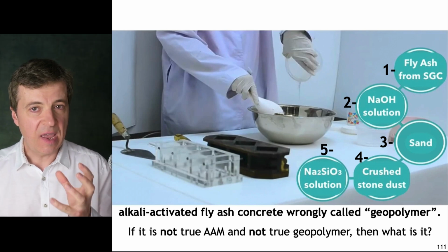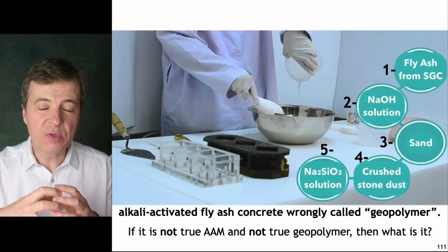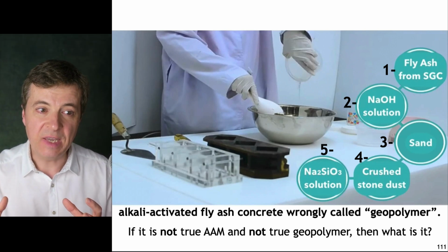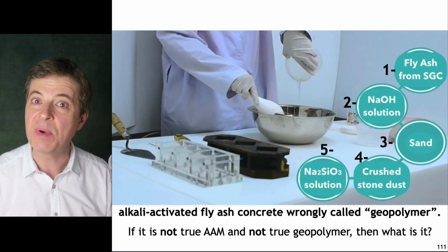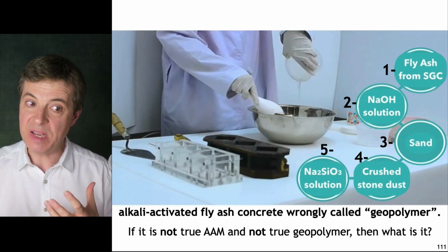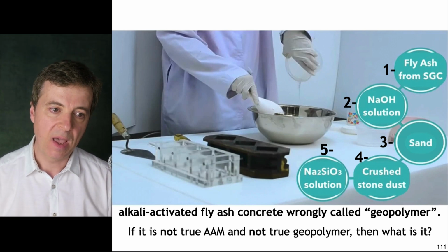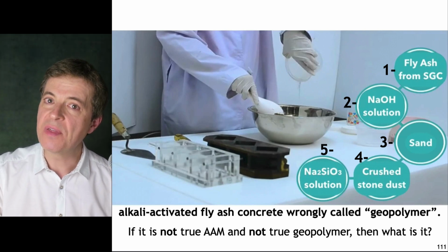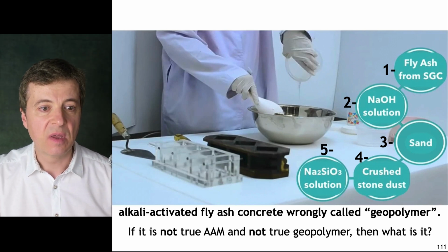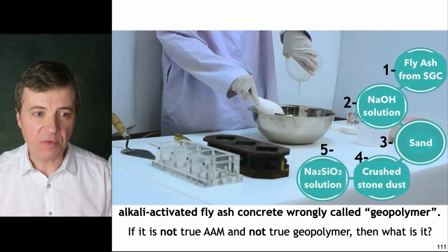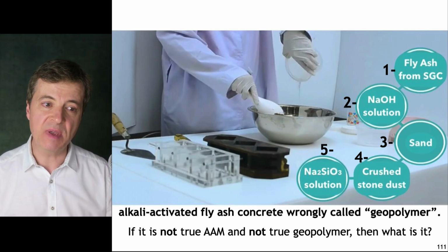You know that NaOH and silicate, when mixed together, will produce a lot of heat, giving the impression that a strong chemical reaction is taking place, and we may believe that it is starting to harden. As a result, everything here is wrong. In the end, there will be a lot of unreacted NaOH and free silicate in the mix.